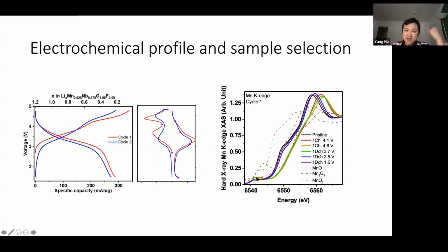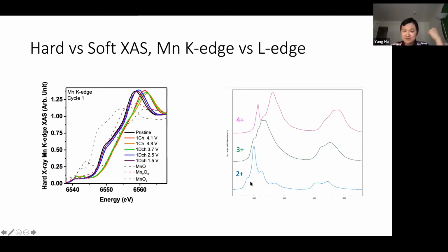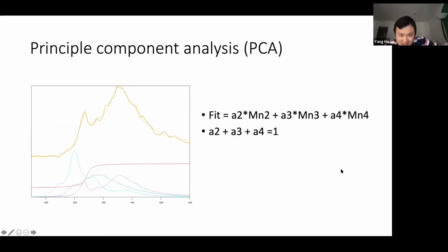So that is the advantage of the soft X-ray. If you look at the reference spectra of the manganese L edge, the manganese 2+, 3+, and 4+ are totally different. Right? We can do a principal component analysis. We obtain an experimental spectrum and do a linear fit with the standard spectra we have. Then we end up with the amounts of manganese 2, manganese 3, and manganese 4 in the sample.